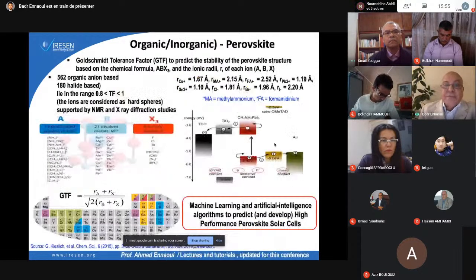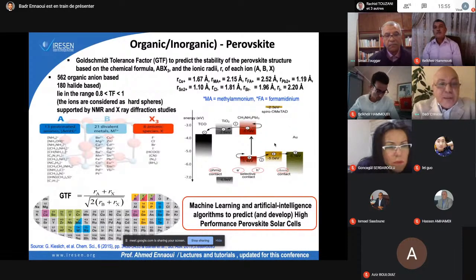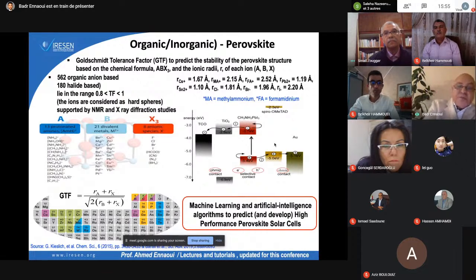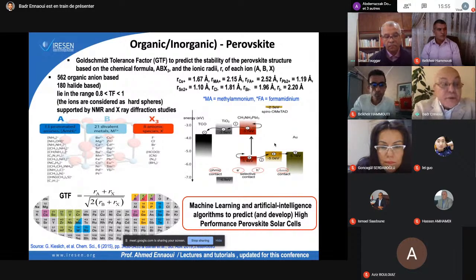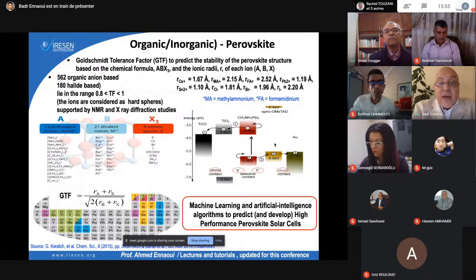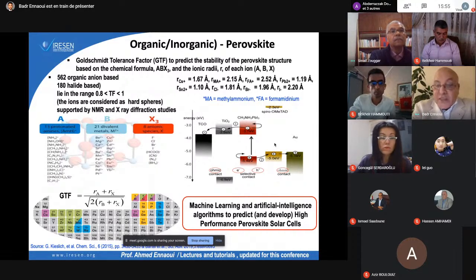The other one here is perovskite. There are plenty of perovskite structures. I put here the whole spectrum, and you can try different precursor A, different precursor B. So the protonated amine, the divalent metal, and the anionic species. So three kinds of ions, and you can try to make the best perovskite solar cell. And you can even use machine learning and artificial intelligence algorithms to predict high performance perovskite solar cells.